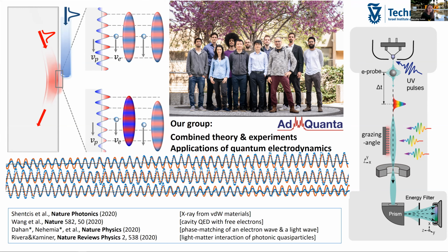So, of course, it depends on what sample. But here's one example. When we look at regular EELS and we want to see a plasmonic resonance, we typically have a small peak, right? It's not always easy to observe. Same thing with excitonic resonances. The typical ratio between a good plasmonic resonance peak and the zero peak will be 1 in 1,000, let's say, for surface plasmons. Sometimes it's a bit better, often it's much worse. This is always a spontaneous effect, the electron emitting some excitation, creating an excitation of a plasmon.